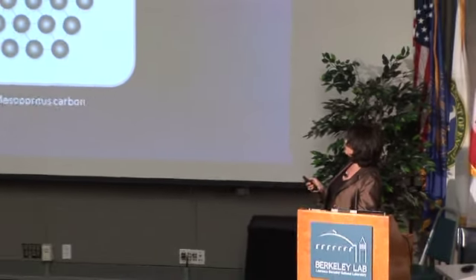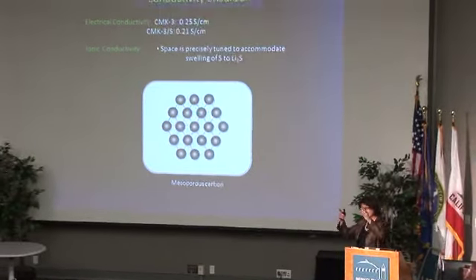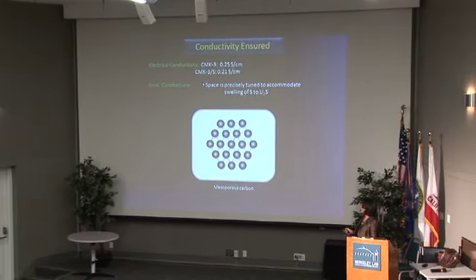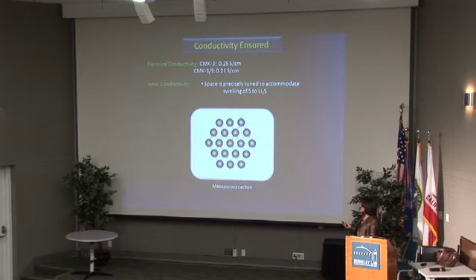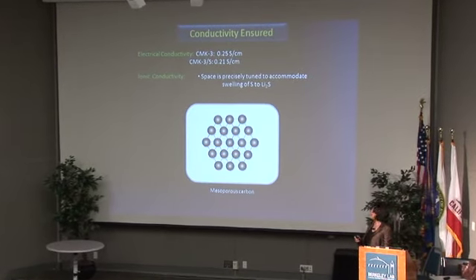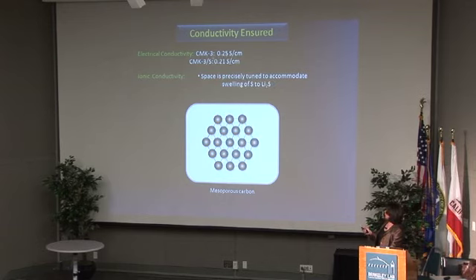For those of you who are not familiar with this, this is work we published in 2009, which we called proof of concept. We organized that carbon, those little micron-sized arrays I showed you about 3 slides previous. They have carbon fibers between them that effectively span organized space, which comprises pores of about 3 to 4 nanometers. This is a fairly easily made mesoporous carbon, which goes by the name of CMK3. It has conductivity of about 0.25 Siemens per centimeter, and when we fill it with sulfur, the conductivity is effectively the same. So it's like inserting a whole array of conductive posts in the sulfur mass.